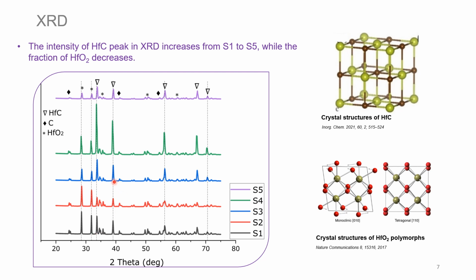With the increase in cross-linking temperatures from 250 to 400 degrees C for samples S3 to S5, the presence of moisture in the cross-linked samples was greatly reduced. As a result, a clear increase in hafnium carbide peaks was observed for all these samples. In addition, traces of carbon materials were also observed in all the samples. Here, the crystal structures of hafnium carbide and monoclinic hafnia are shown, which are presumably present in these samples.